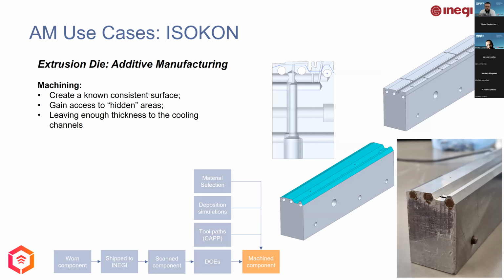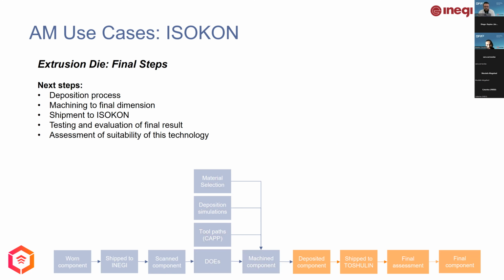Using the knowledge gathered on the previous steps, the geometry for machining can be defined. The objective here is to create a known and consistent surface and to gain access to areas that would be impossible to reach using the original geometry. The goal is to remove the least amount of material, maintaining enough thickness to the cooling channels below the surface. Having the parts machined, the next step in this repair would be to perform the deposition of the new material, machine the parts to their final dimensions, send them back to ISOKON for testing and evaluation, and finally perform an assessment of the suitability of this technology in this use case.